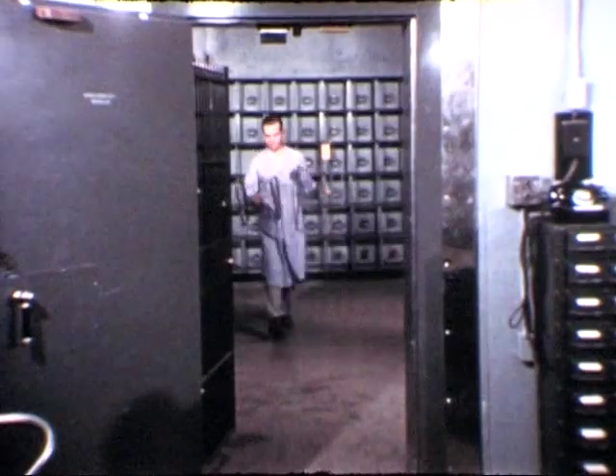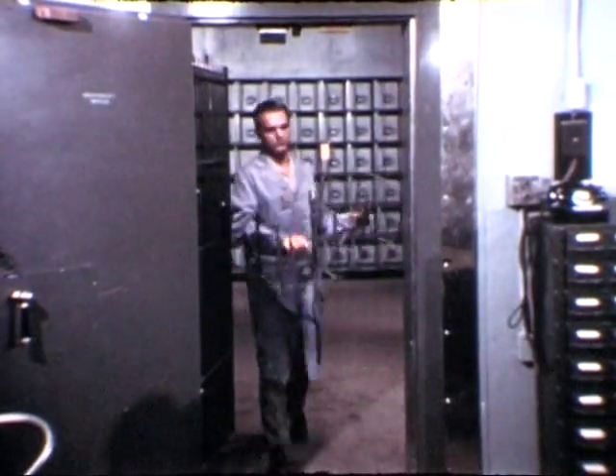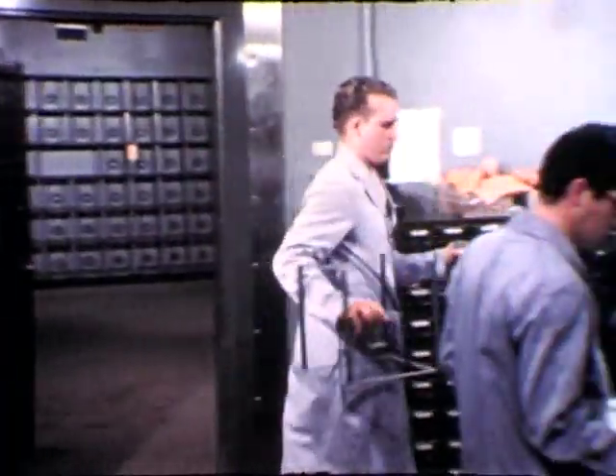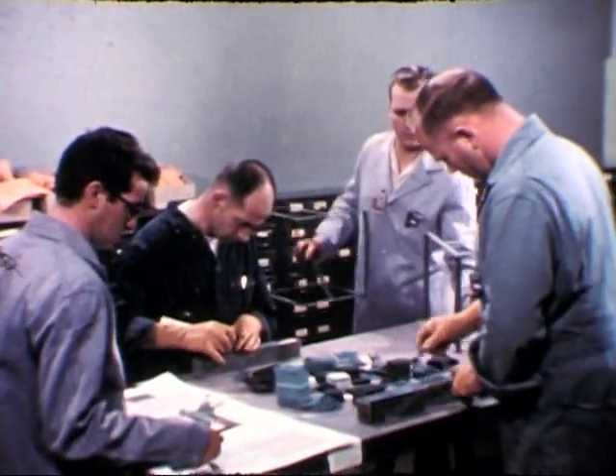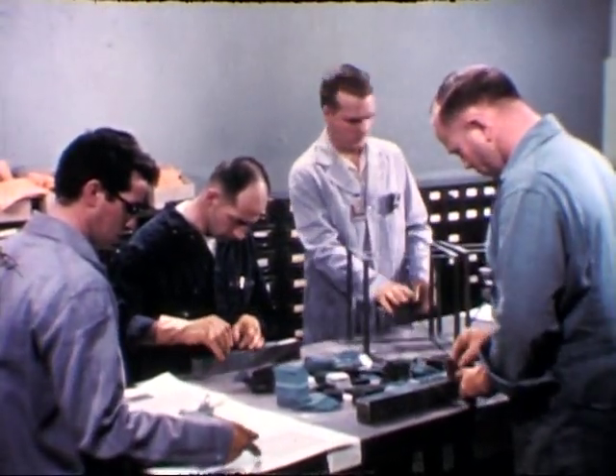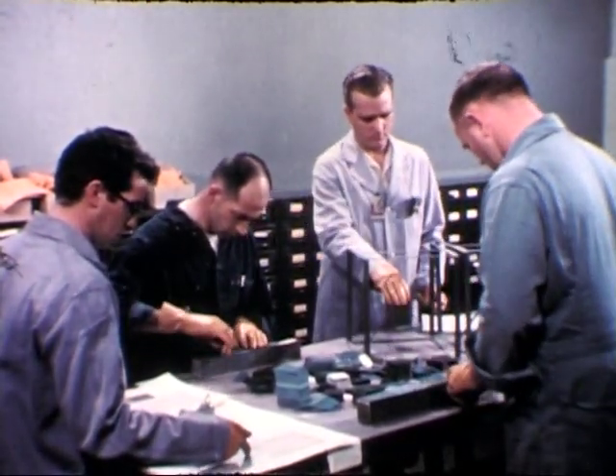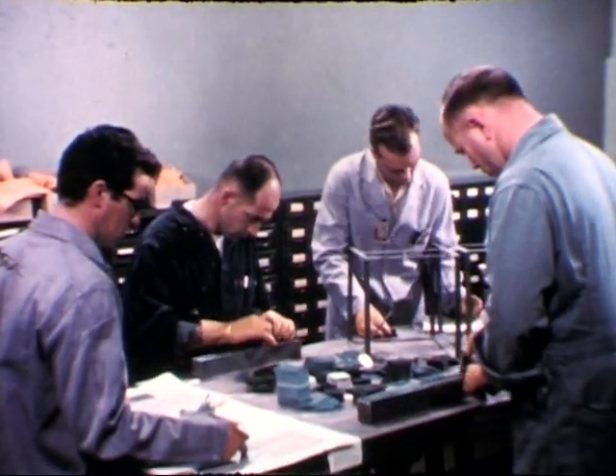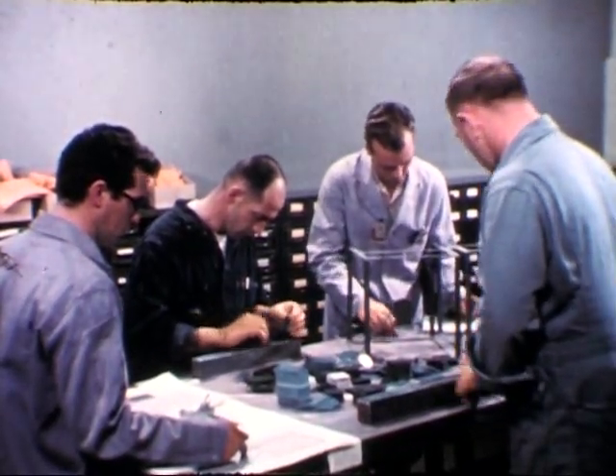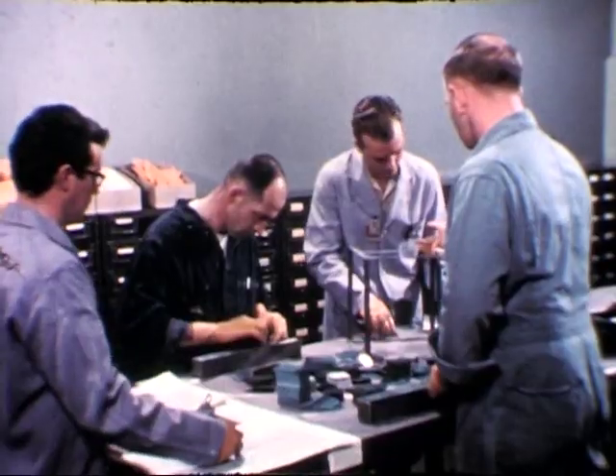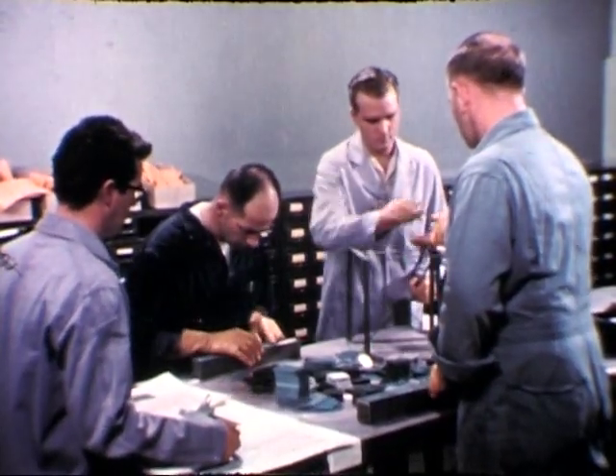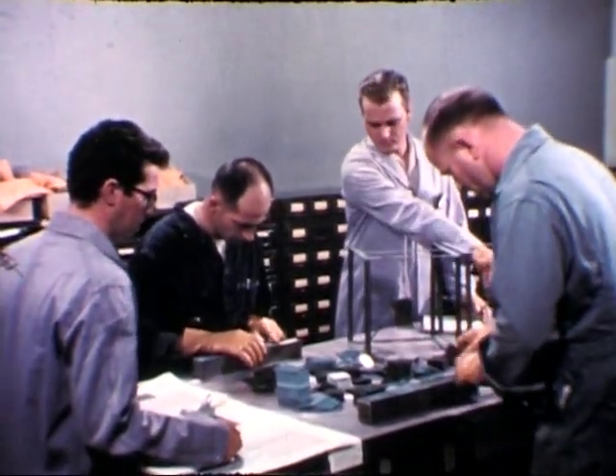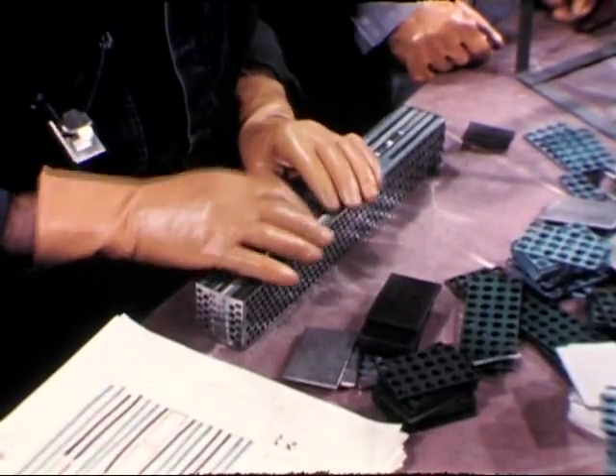The highly enriched uranium-235 in the form of 1/8 inch thick plates is color-coded red to distinguish it from the depleted uranium, which is black. Only 2 drawers may be loaded at any one time on the loading table. Since the distribution of materials in a drawer has a pronounced effect on reactivity, the desired arrangement must be maintained.